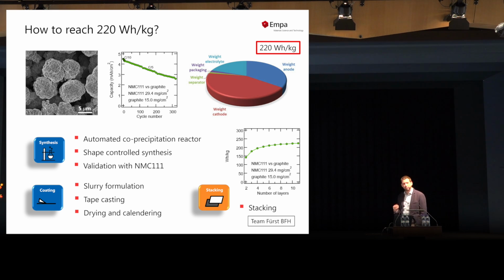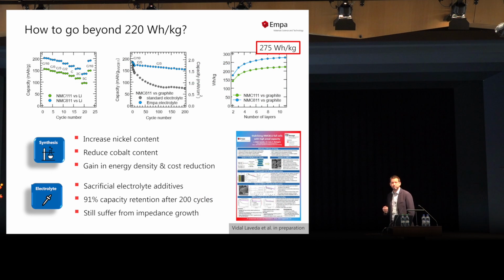Okay, so I showed you how we can reach just the starting point of the SCCER. That took us a little more than a year to get to this point, and we are not yet fully there. But how do we get any further? We have to reach 275 watt-hours per kilogram by the end of the SCCER. So the approach we have been choosing is going back to the materials level, the synthesis level, and we are now focusing on increasing the amount of nickel in the cathode materials.